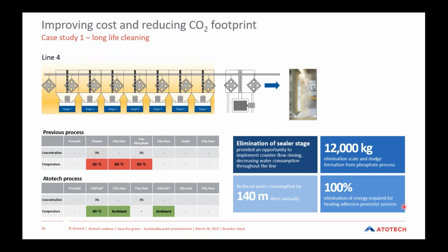So here's the example of their paint line. And we'll focus here on the bottom left side of the page, looking at some of the process benefits. Here we were able to reduce the operating temperature of the cleaner from 50 degrees Celsius down to 40 degrees Celsius. We're also able to eliminate the heated rinse that came after the cleaner, which was necessary for their process, and also able to completely eliminate the heat requirement for the conversion coating. Here you can see the iron phosphate was operated at 50 degrees Celsius, and with the Interlox conversion coating, able to operate at ambient temperature.